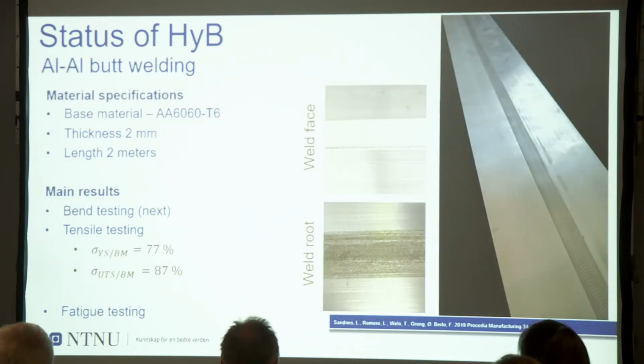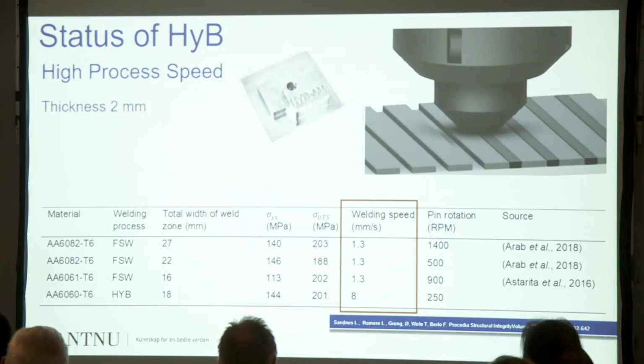So these are some results and some pictures of the weldments for 2 millimeter thickness, with the efficiency of the weldments with respect to the base material. The advantage is that for HyB we have a clear advantage in terms of speed and flexibility. And in particular, if you compare the speed of friction stir welding with the speed of HyB, we have a very nice advantage for HyB, which has a speed of 8 millimeters per second. Instead, the friction stir welding is only 1.3.